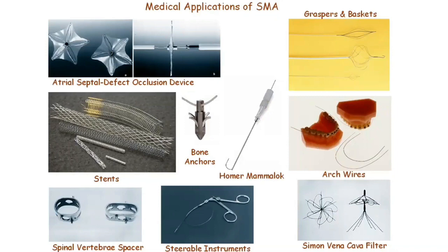Because of the titanium, forming a titania layer on the top, it's biocompatible. Though there are some who feel that nickel can cause some issues, by and large it is the titania that protects the nickel titanium, and you find a lot of applications in the human body. And for superelastic, one can think, if you want steerable instruments and you want to take them through those difficult areas of the human body, you can have such kind of instruments, or grasp something which you want to retrieve from the body.